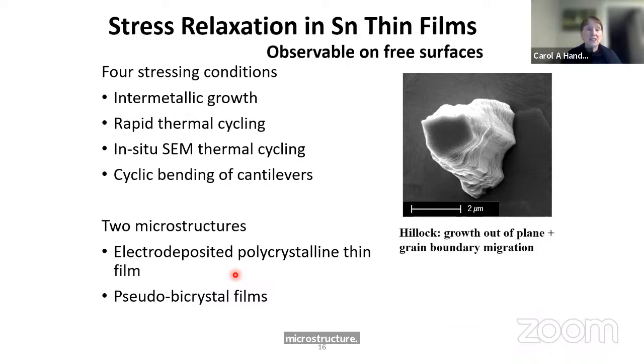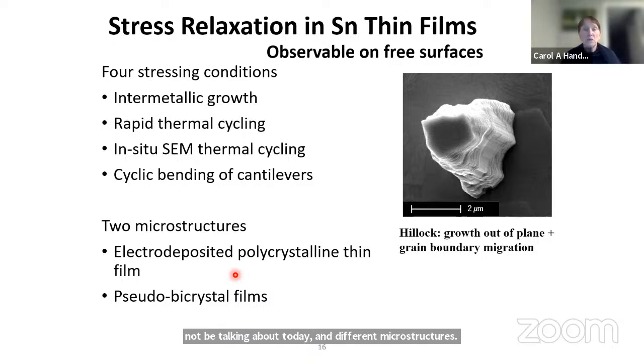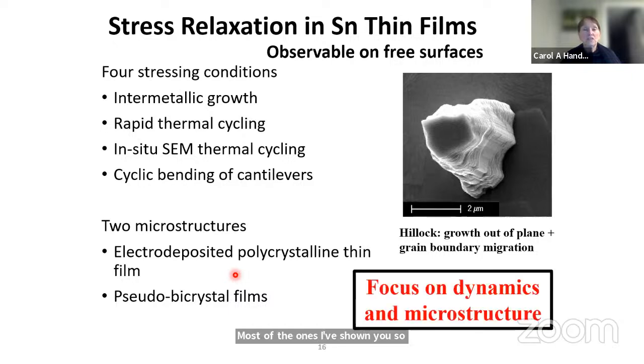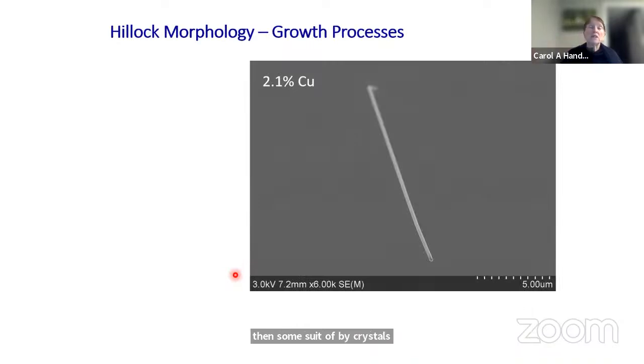So there are 4 different conditions that we've explored: intermetallic growth, rapid thermal cycling, and in situ SEM thermal cycling, which I'll not be talking about today, and different microstructures, electrodeposited polycrystalline thin films. Most of the ones I've shown you so far are that way, and then some pseudo bicrystal thin films. So focusing on dynamics, we know we can control the microstructures that form by changing the characteristics of the film. So this film has 2.1% copper in it. There are intermetallic particles that are pervasive through the film, and so this whisker grew out of the film with little or no grain boundary migration. So you can suppress the grain boundary migration by pinning the grain boundaries.